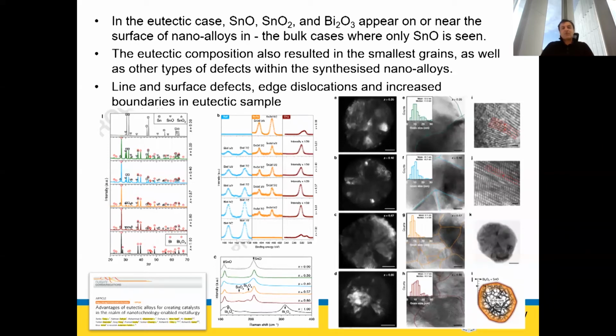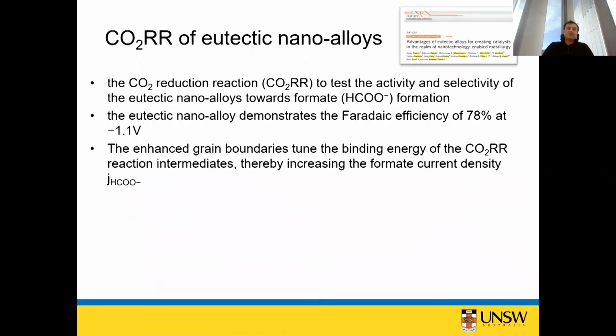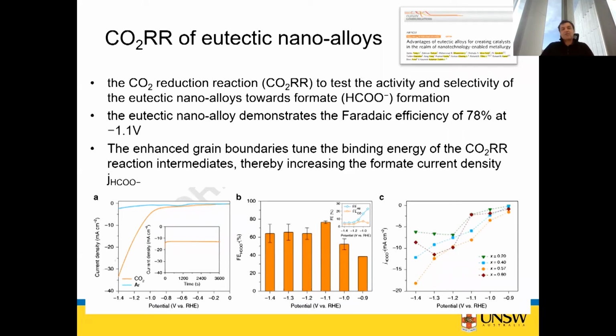The core has more grains. We have more grain boundaries for this eutectic alloy, and we have lots of higher density line surface defects and edge dislocation. All these things say that we have a very good catalytic metallic material which is covered with metal oxide. We use it for CO2 reduction reaction. This is not in liquid form, this is in solid form. So this is classical electrochemical reduction into formate, which is a liquid. The voltage which is applied is very low, Faradaic efficiency is very high, 78%, and the enhanced grain boundaries, using the liquid metal process for the formation of these nanoparticles, help us. So it's not all about liquid, it's about the process that also can improve and give you opportunity to make the material better for catalysis.